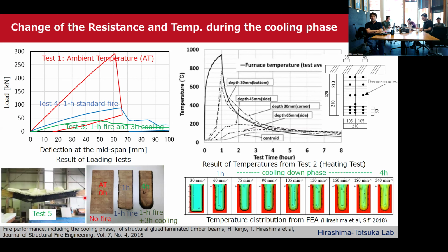Looking at the photos of the beam cross-section after heating tests, the change in charring depth was small during the cooling phase. So the decrease in the resistance during the cooling down phase was due to an increase in internal temperature. The temperature at the center of the cross-section, the centroid, just after heating for 1 hour was close to ambient temperature.